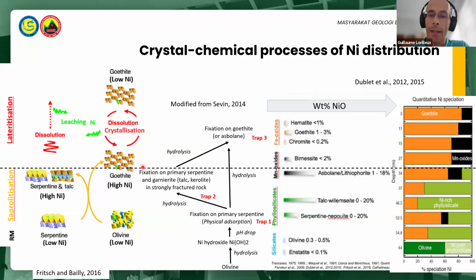At the base of the limonite, in what is called a transition zone, manganese oxides may incorporate an important part of the nickel. This zone contains dark manganese and cobalt-rich concretions that include the phyllomanganate family: asbolane, lithiophorite, and birnessite. In limonite, nickel is mainly hosted by iron hydroxide, predominantly goethite. The nickel in goethite may account for about 75% of the total nickel in limonite, whereas asbolane and lithiophorite may account for about 25%.